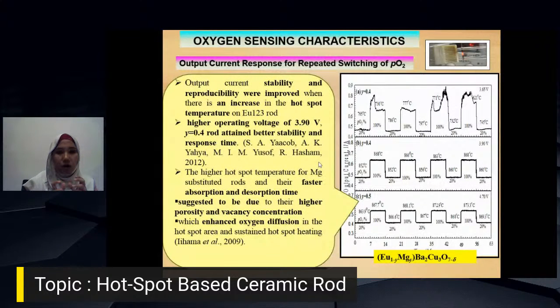For this faster absorption and desorption, it is suggested to be due to the higher porosity and vacancy concentration on the formation of the hotspot in the material of the ceramic rod, which enhances the oxygen diffusion in the hotspot area and sustains hotspot heating. So this is an example of the glowing of the hotspot during the changes of the oxygen concentration.